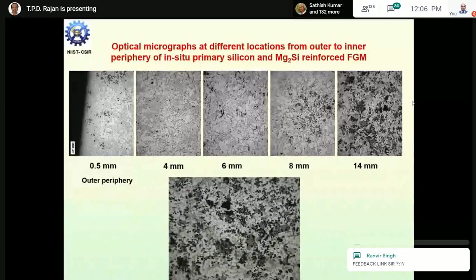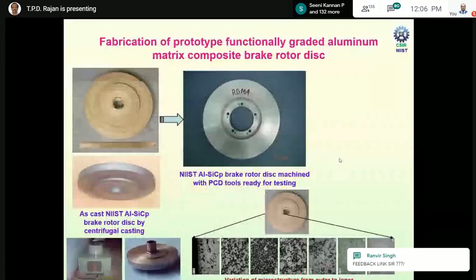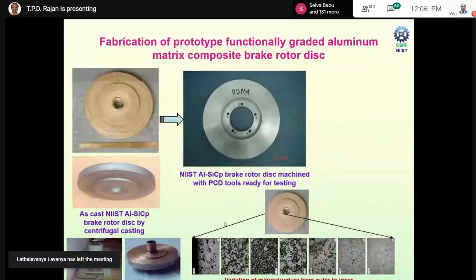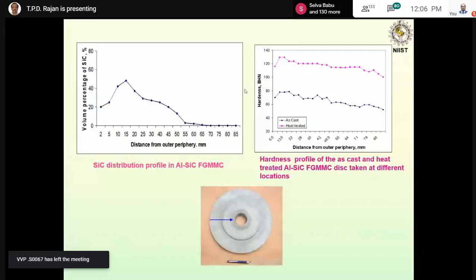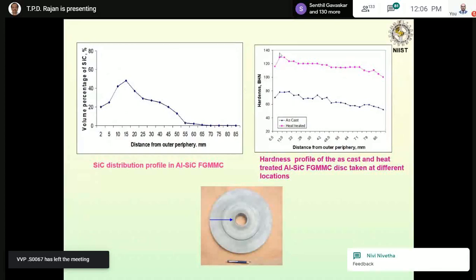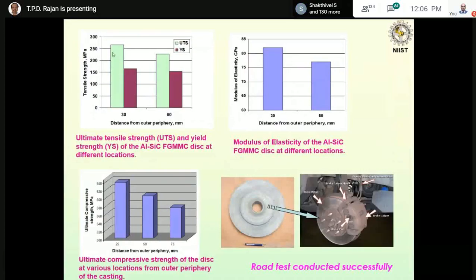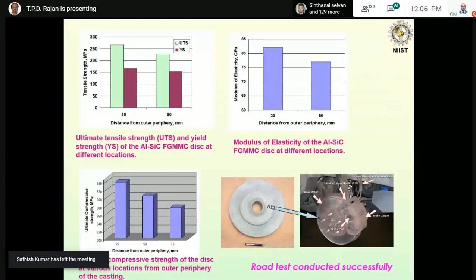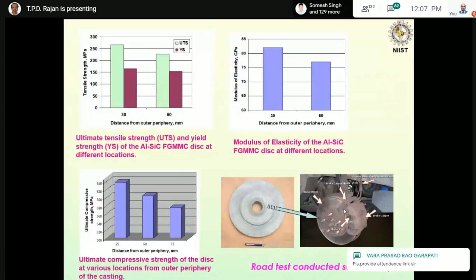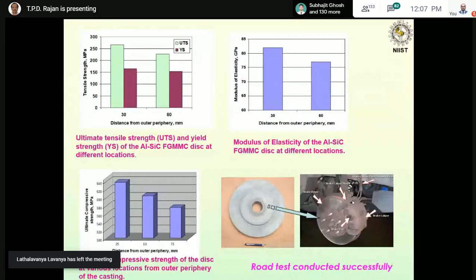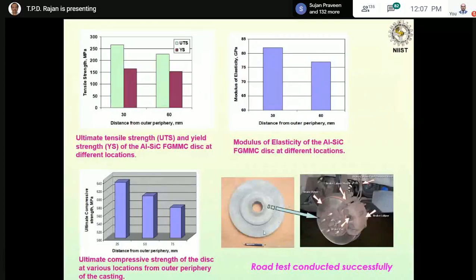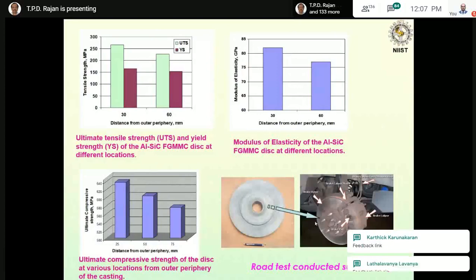This is also a centrifugally cast primary silicon and Mg2Si system. This is a typical brake rotor disc, a centrifugally cast disc, which has a particle concentration in the braking region. So the volume fraction is very high in the braking region, and this enhances the hardness, tensile strength, modulus of elasticity, and compressive strength. That means the properties in the braking region are very high. Once you apply the brake and the brake pad comes in contact with the rotating disc, this exerts a high compressive force and friction force. The presence of silicon carbide increases the stiffness as well as the wear resistance. So your braking can be there, but the main requirement is light weighting. You can use an aluminum composite, and the disc is one third the weight of the cast iron disc.